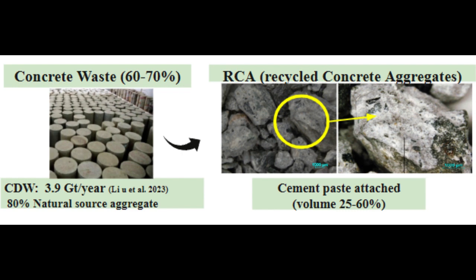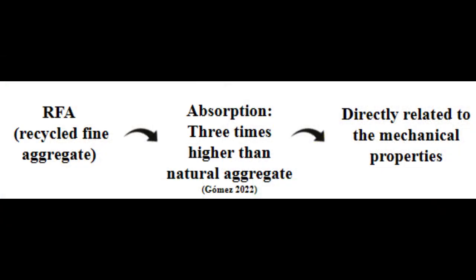The resulting product contains cement paste adhered to its surface, approximately between 25% and 60%. This cementitious paste contains portlandite, a calcium-rich chemical compound that includes hydroxide. Due to the presence of this cementitious paste, the recycled aggregate has high levels of porosity, up to 3 times higher than natural aggregates. This porosity requires more water, leading to an increased water-cement ratio, which directly impacts the mechanical properties of the material, specifically its compressive strength. As a result, these aggregates cannot be used for structural purposes.